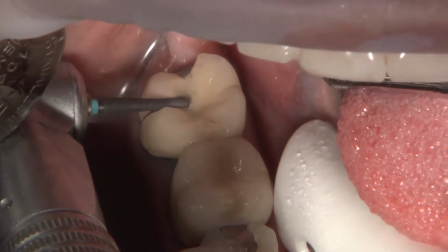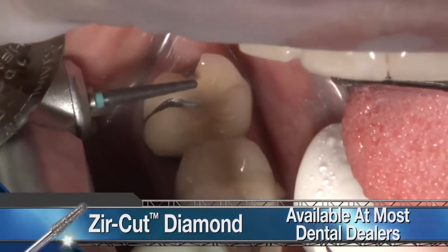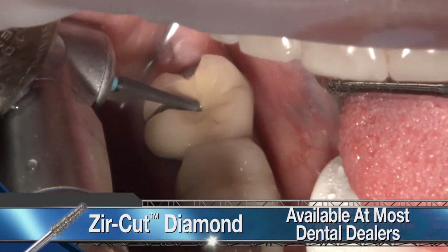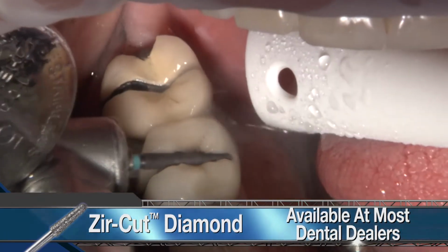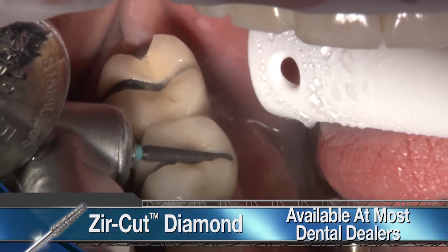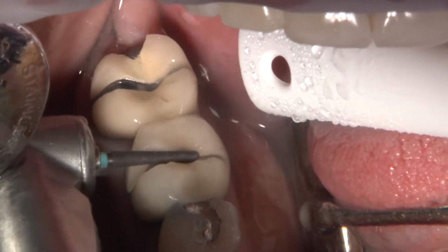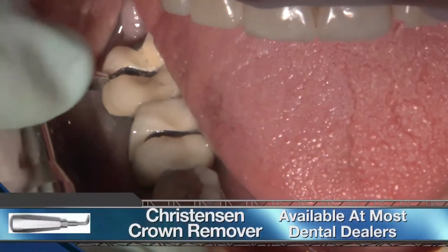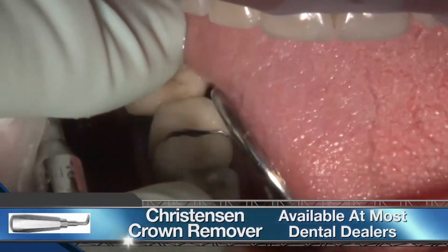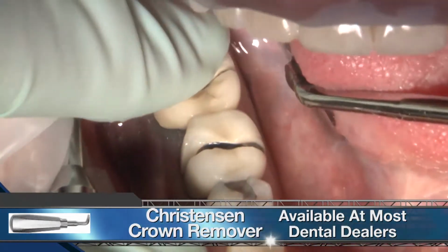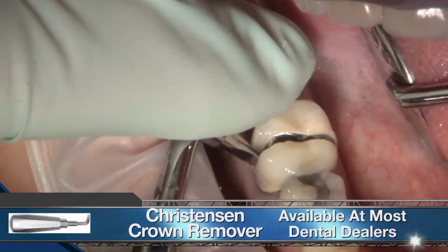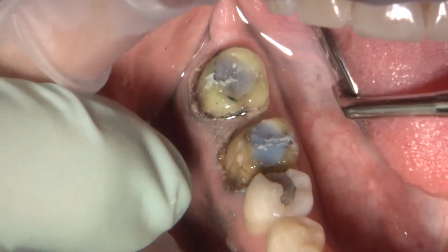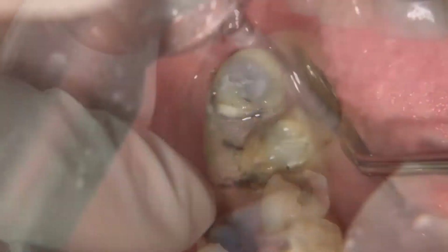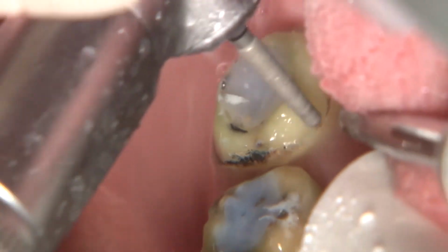Here is the lower right that had 3 defective restorations: a fractured porcelain on distal of 31, marginal leakage under both PFMs, and recurring decay under the amalgam on number 29. The crowns are cut off using a Zir-Cut bur and forced open with the Christensen crown remover. After taking away the defective PFMs, we can appreciate the amount of leakage that has occurred between the tooth and the crown interface.